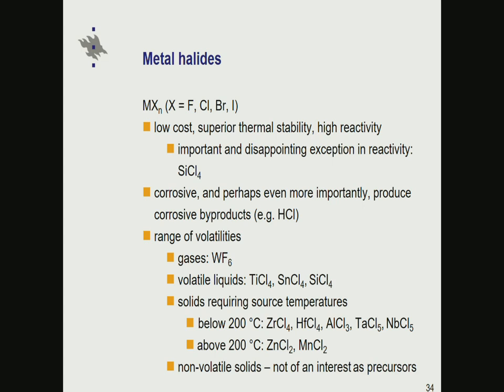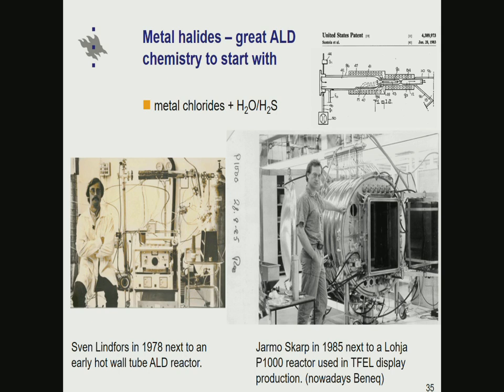Metal halides exhibit a range of volatility. Some of them are even gases, some are volatile liquids, and some are solids which require source temperatures. In several cases of what has been used in ALD, below 200 centigrade is enough, actually closer to 100 rather than 200. But sometimes one needs to go even to 500 centigrade, and that has been possible. Some of those are non-volatile solids which are not of interest as precursors, unless you do something which I will show you shortly as well.